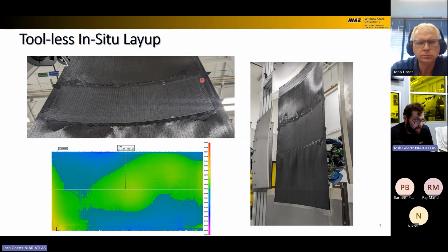So here's an example single curvature part that we manufactured on this machine. Extending above and below the edges I'm highlighting here is just that essentially 3-layer thick base ply, and then we've built up to a 12-ply thick panel in the center here. And then we have some T-scan data to basically show the accuracy of the curvature of this part.